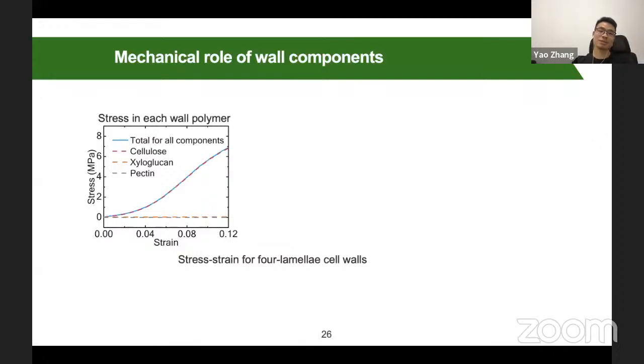Now we try to understand the mechanical role of wall components. We have introduced that the primary cell wall has three main components. One is cellulose. The cellulose is stiff because it has a very large persistence length. The xyloglucan and the pectin are flexible. I think the persistence length of the xyloglucan and pectin is around 10 nanometers, compared with the cellulose microfiber, which has a persistence length around 1 micrometer. So it's much larger, much stiffer.